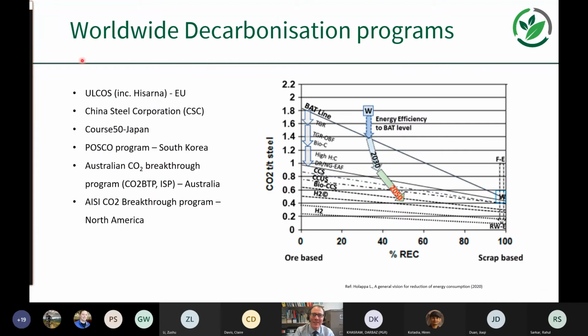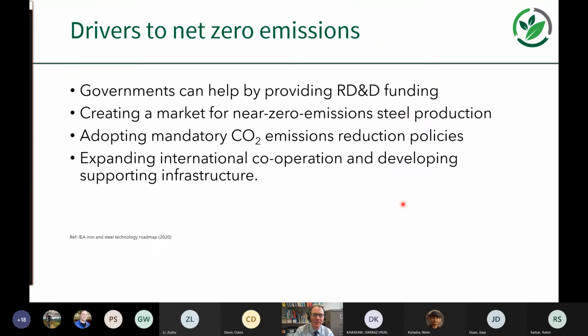And then these worldwide decarbonisation programs that I've listed on the left there, the ore-based higher specific intensity carbon dioxide intensity processes, they're driving towards changes in evolution in the blast furnace, top gas recycling, oxygen blast furnace, using biomass, using carbon capture, using hydrogen to drive this CO2 produced per ton of steel. So the trend is from where we are currently with the worldwide average to utilize more scrap-based production and to move this down to a lower specific CO2 production per ton of hot metal.